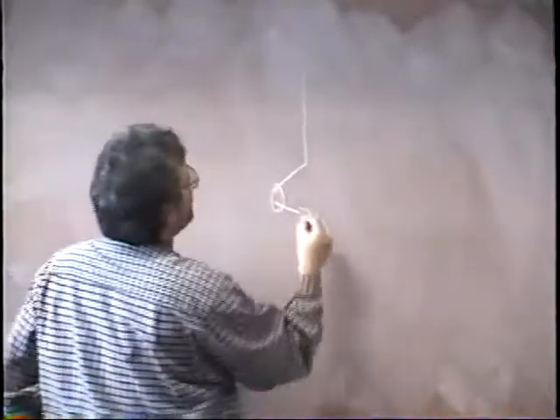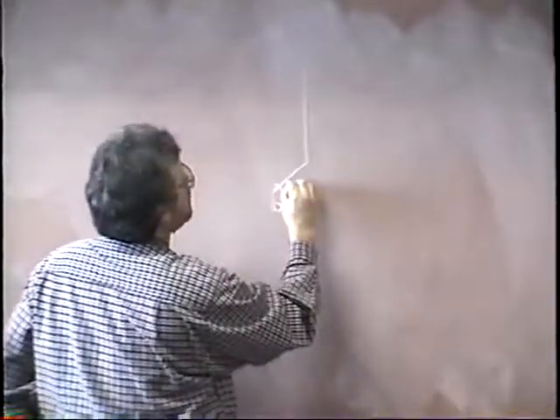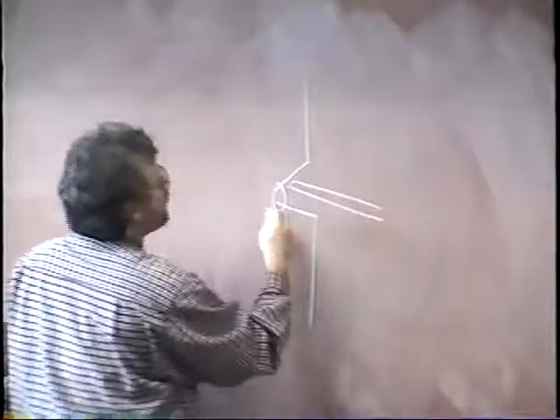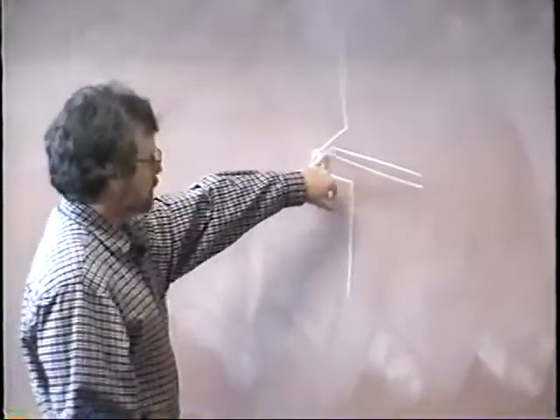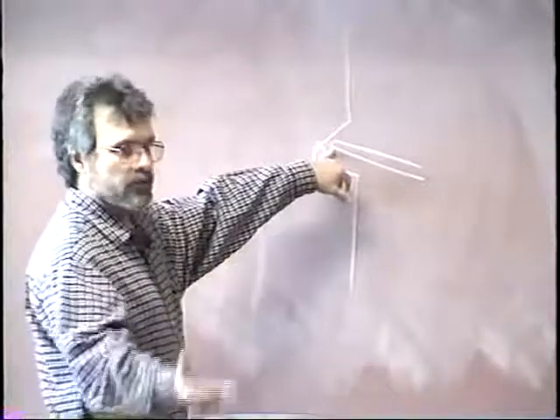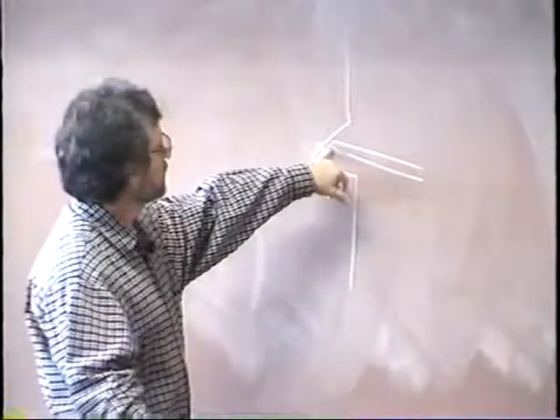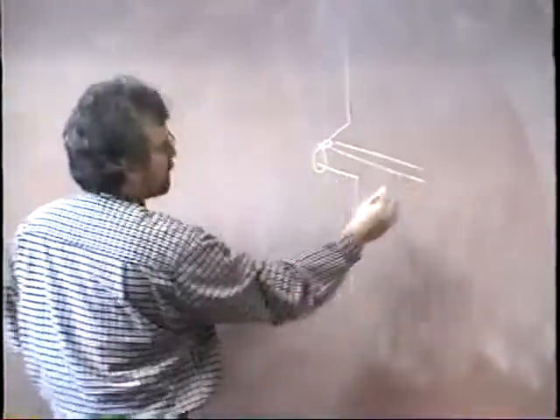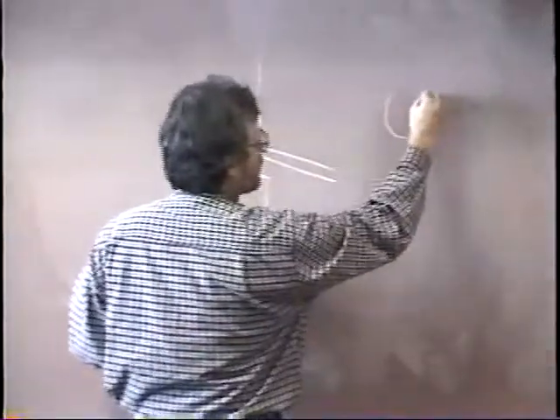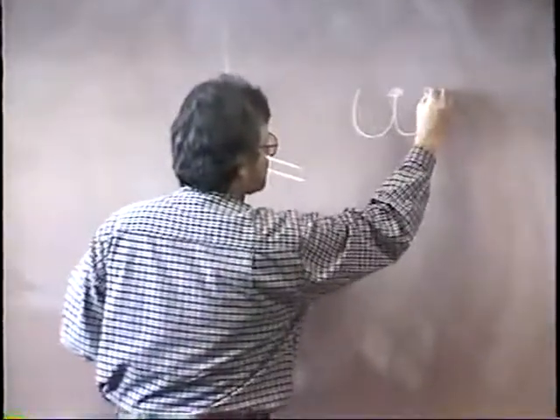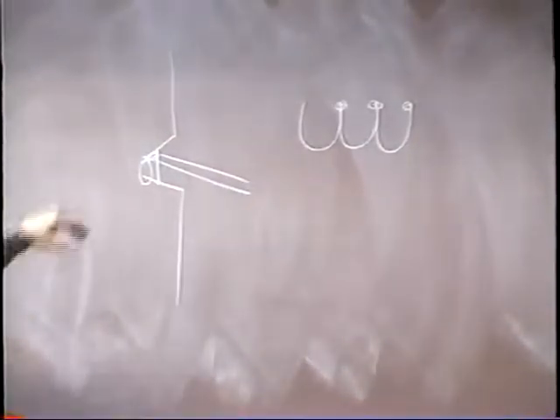The weave I like to use is the W technique. If you got your root pass in there, I actually like to use a bit of an up angle, and you pause on the upper side here to allow some of the welding electrode to melt. Whether it's plate in the horizontal position or pipe, you're going to deposit some weld metal here, and then you're going to come down, back up, and pause. Come down, back up, and pause. Just like this. This is the W technique, and it will deposit that second layer, and it will make it flat if you use it properly. And this is what I like to teach.